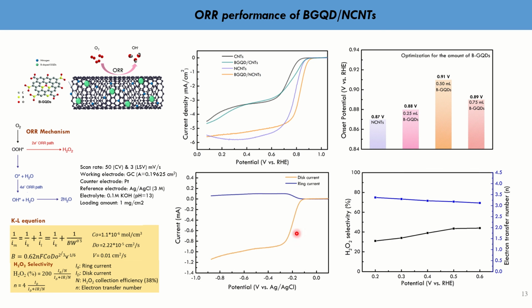For the ORR performance, first, from the LSV, the onset potential of BGQD/NCNT is 0.91 volt, superior to CNTs. The optimal result shows that adding 0.50 mL of BGQD gives the best onset potential. In order to check that our reaction follows the 4-electron pathway, the disk current and ring current were also measured. Using the Koutecky-Levich equation to calculate the electron transfer number, the result is 3.5, indicating that BGQD/NCNT possesses a great ORR performance.